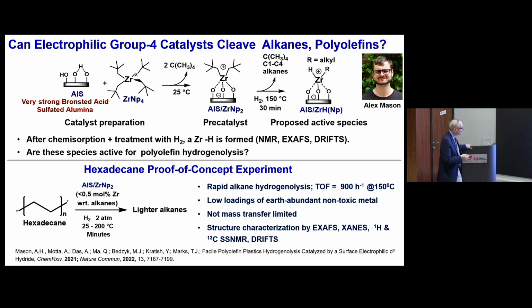And the idea was to have a very strong Bronsted acid. When it's reacted with this early transition metal alkyl, some of the zirconium carbon bonds are cleaved, protonolyzed, to get something that we sort of envisioned would look like that. And then we wanted to see whether it could, under hydrogen, cleave polyolefins. And so we started with hexadecane.